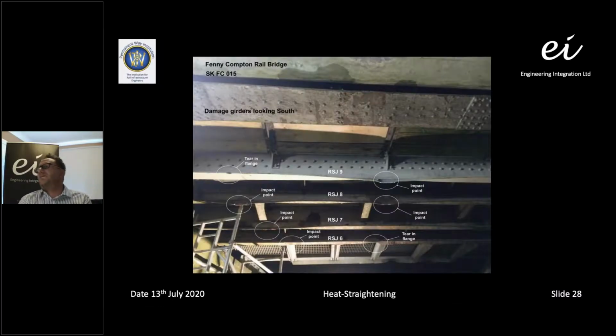So going back to the very first slide in the presentation, we look again at the typical railway structure that has been impacted. And you can see there that we've got 6 girders that have been impacted at different times. The impact points are actually almost 8 feet apart. So therefore, we're assuming that the impact was caused by the hard spots on a container being carried on a low loader. And obviously that's what we would be looking to restore the shape of using heat straightening.